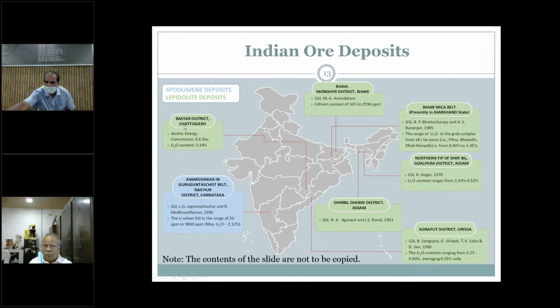And other deposits: the Bastar district in Chhattisgarh contains lepidolite, and the maximum lithium content shown in the literature is 3.34 percent. In the state of Odisha, the Koraput district is a bit inferior in lithium content, with 0.25 to 0.8% Li2O. And recently we started working on the Bihar Mica belt, which has lithium content varying between 0.4 and 1.35 percent. And in the northeast region also there is some occurrence. Most of these occurrences are in forest areas and associated with pegmatite occurrence.